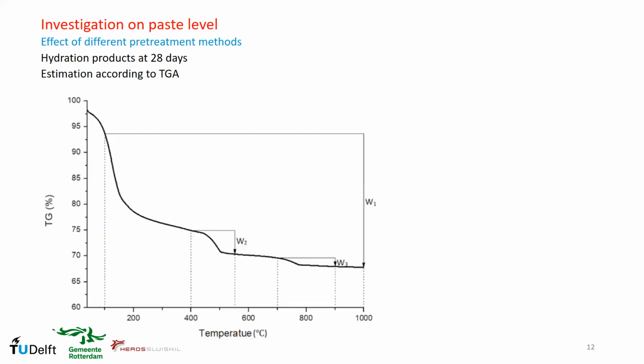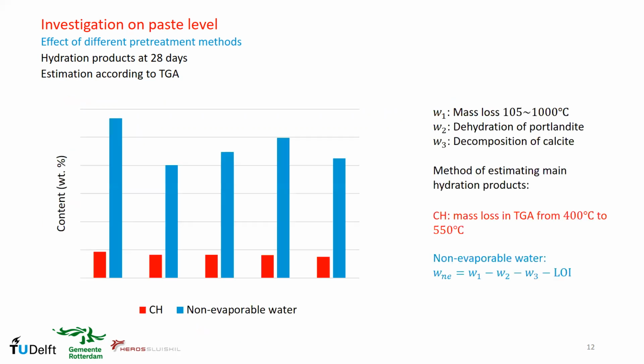Also, the estimation of the amount of hydration products at 28 days according to the TGA measurement. Here we found that the amount of portlandite and the non-evaporable water is in agreement with the compressive strength study.